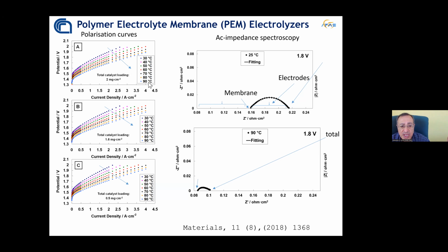Here we have a limitation, because we cannot exceed 90 degrees Celsius, otherwise water will be boiling and the membrane will dry. So to have good stability, we need some temperature in between. Temperature and catalyst loading are relevant parameters affecting the efficiency of the system and the operating current density.